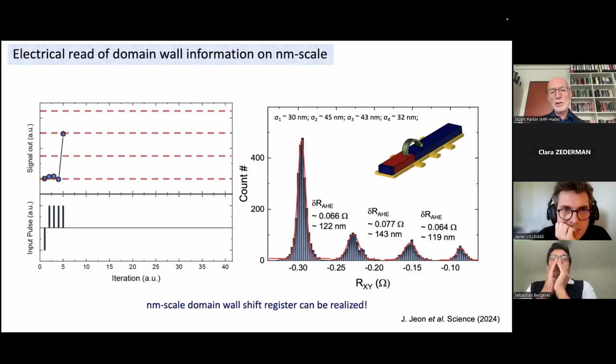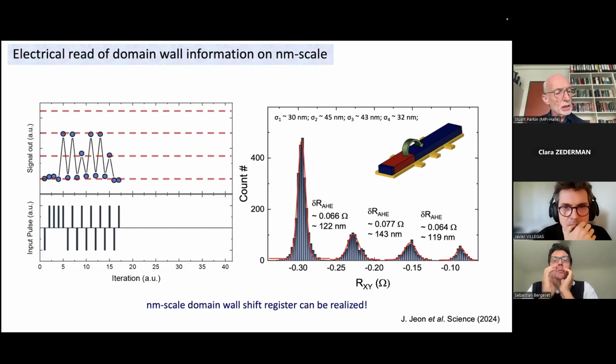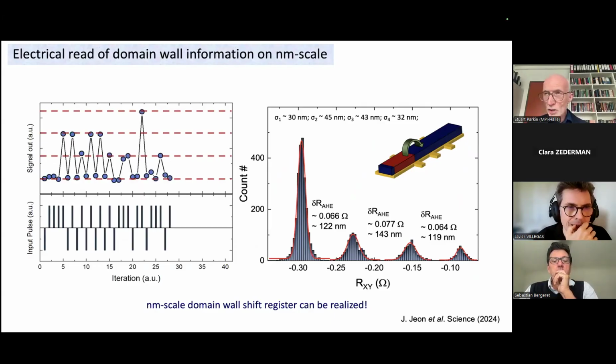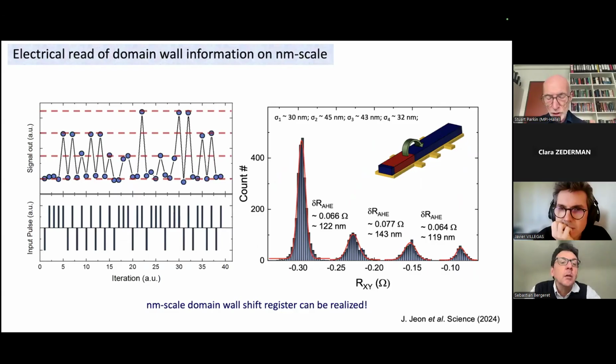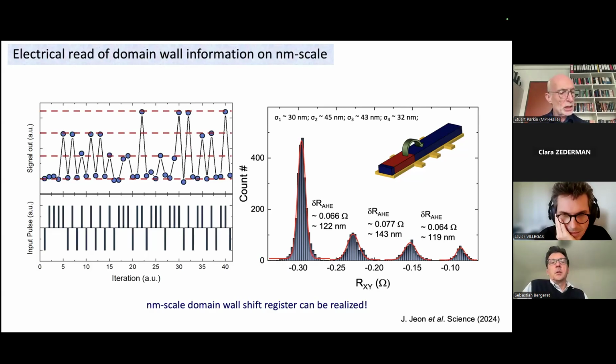And then we also realized that we could position one domain wall precisely along the racetrack with an accuracy of a few tens of nanometers. And we could position one domain wall with respect to another, putting them close together, to about 100 nanometer precision. So we believe these numbers, the ability to position a single domain wall to an accuracy of a few tens of nanometers in a very narrow racetrack, is basically what is needed to build a racetrack which is technologically relevant. Anyway, you can read more about that in this Science paper.